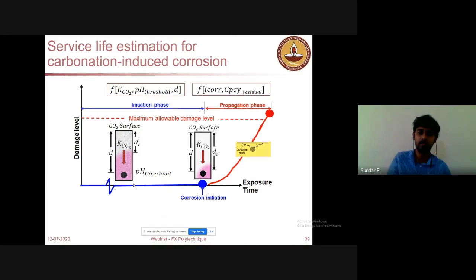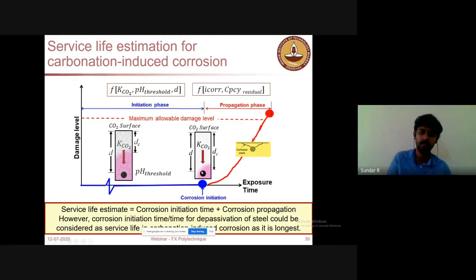Similarly, for carbonation induced corrosion also, this could be adopted. Here the critical parameter will be the carbonation coefficient. To calculate the carbonation coefficient, you need to have an accelerated test or a natural test. For different binders, you have to calculate this carbonation coefficient, and then determine the corrosion initiation time, which is the time taken for the carbonation front to reach the steel. That might have a higher possibility of corrosion. So this has to be calculated for carbonation also.